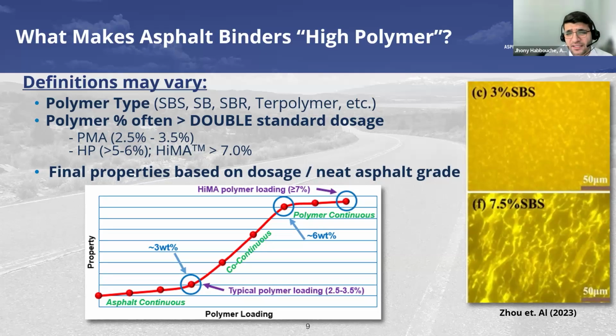And the final properties of the resultant binder, the base binder with the polymer, is really dependent on the polymer loading. You will have an asphalt continuous behavior up to a polymer content of 3%, and that's where the conventional PMA is. You will have a co-continuous behavior between your base binder and your polymer. And then at the end, once we hit that 5, 6, or 7% polymer content or loading, that becomes a polymer continuous behavior in the resultant binder.